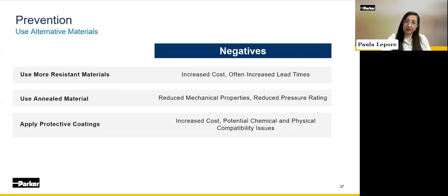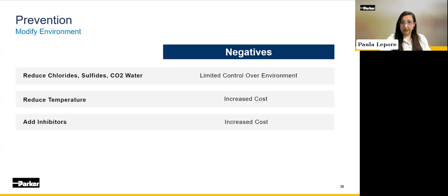For materials, we can use higher alloys, annealed alloys, for example, and apply platings or coatings. Often this comes at a higher price, prohibitive lead times, and reduced pressure ratings. And we have very limited control over the environment, of course. All we can do is try to use elements such as corrosion inhibitors, try to operate at lower temperatures if possible, and try to reduce the corrosive element concentration. All this comes at increased cost, also with operational downsides.